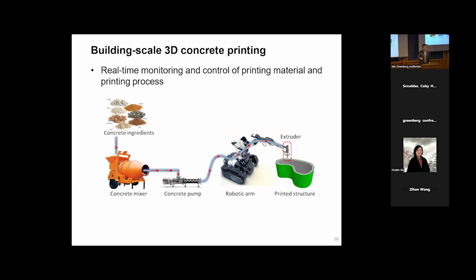The printed fiber is like sensory nerves that can provide real-time monitoring of the printed structure. We did the 3D concrete printing. We are talking about the building scale 3D concrete printing. So concrete is heavy, right? The high density. So if we print the structure very quickly, before concrete is hardened enough, gains enough strength, the bottom layers will be deformed, right? Because there's compression. So we use this sensor technology based on the maturity theory. We can monitor the strength of concrete in real time, and then we can maximize the printing efficiency. We know, okay, if we don't exceed this rate, then we will be okay. So we can optimize the manufacturing process, and at the same time, the printed sensor can provide long-term monitoring.